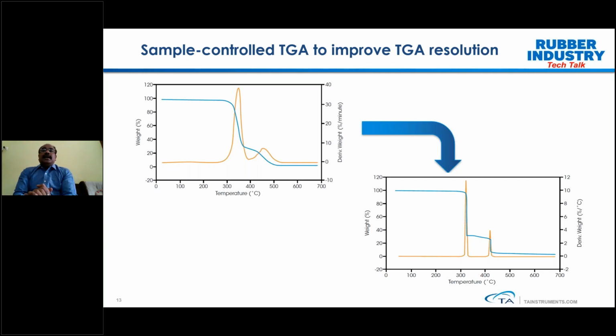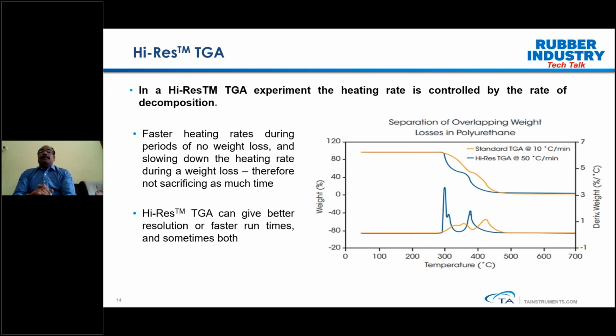Here we can see an example for polyurethane samples. Just for information, we have taken a polyurethane. If you see the decomposition, the standard heating curve, the orange color curve, is running at a heating rate of 10 degrees centigrade per minute. The high resolution TGA is starting at 50 degrees centigrade per minute. So what we see is a much sharper peak, and you can see the clear shift of your decomposition pattern.